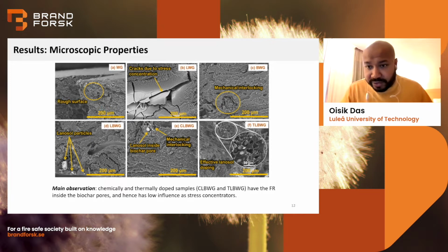Number C, where we have only biochar, no fire retardant, we see that a biochar particle has a mechanical interlock with the plastic, which is quite a known phenomenon, understood from my previous work in my PhD, that when we add biochar to any plastic, the pores of the biochar interlock with the plastic, improving the mechanical properties. And with dry mix, which is number D, we see the particles are on the surface of the plastic.